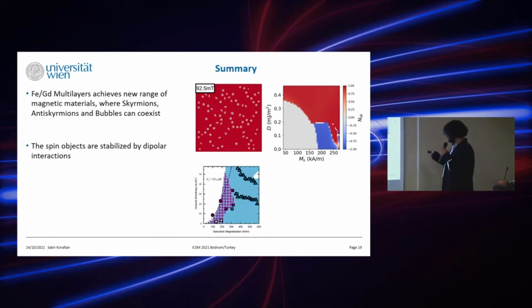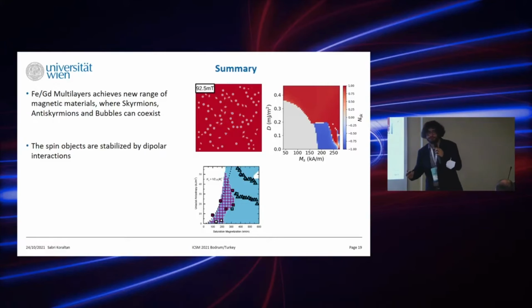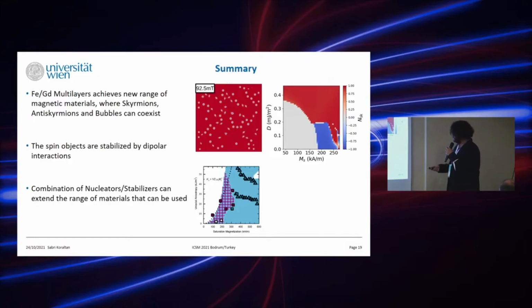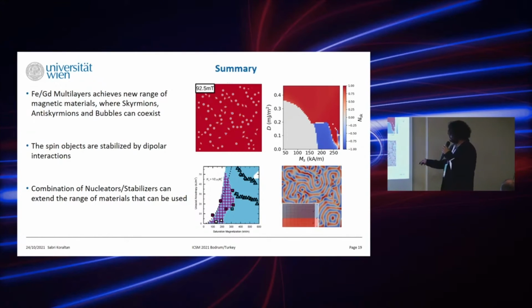They are dipolar stabilized, and now we have a recipe of which materials and which material parameter ranges we can use in order to again see this coexistence. And we have seen that it's not only that we have to use one material, but we can make use of mixed concepts like nucleators and stabilizers in order to achieve the same effects.